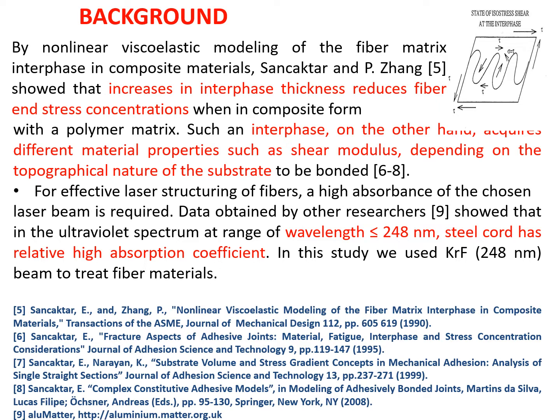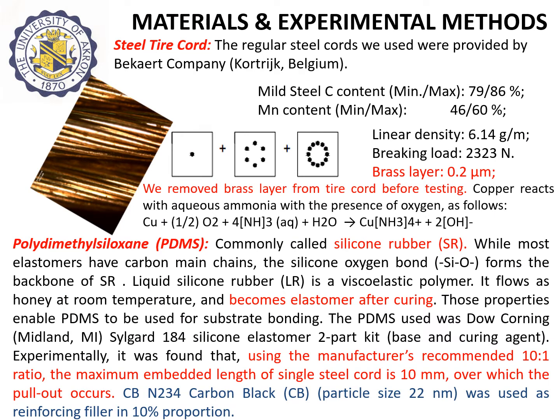Another issue that we pay attention to is to make sure that the wavelength that we use is adequately absorbed into the substrate. And in this case, 248 nanometer wavelength we use is appropriately absorbed by the steel cord. The steel cords we used were obtained from Bekaert company in Belgium. This cord is spirally, helically wound multi-layer cord, as shown in the middle pictures here. And the properties of the cord are also shown on the upper right.